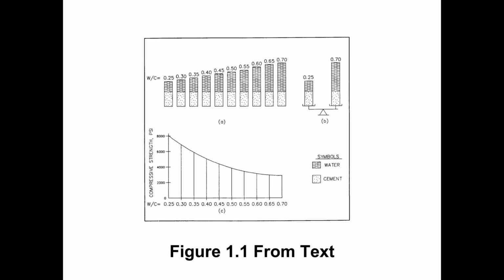So that's one of the key drawbacks to using a high water cement ratio, is that we lose concrete strength, we lose compressive strength in those samples. And another issue that I just alluded to is that the higher your water cement ratio, the more lattice-like the structure within the concrete. So that means that there's more space within the concrete that can be occupied by other things, such as water and air. And so not only does that make the concrete weaker, but it also makes the concrete less durable. It's more susceptible to water freezing and causing damage. It's also more susceptible to penetration by other liquids such as sulfates, acids, chlorides, anything that the concrete comes in contact with in its environment. It's going to be more susceptible to absorbing that adverse material, which could negatively affect the durability of the concrete over a long period of time.